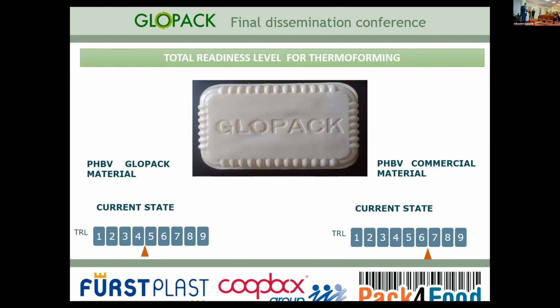If we speak about the TRL for the thermoforming process, we can consider that the current state for the Glopack material is a little lower, only because we didn't have the time or the possibility to make some thermoforming tests with that material. So on the scale of readiness, it's lower. If we compare with the PHBV commercial material, we were able to produce trays, so the level is higher. Not at industrial scale, it was made in the laboratory, but we were able to use these trays also for the shelf life test. So the total readiness level is higher.